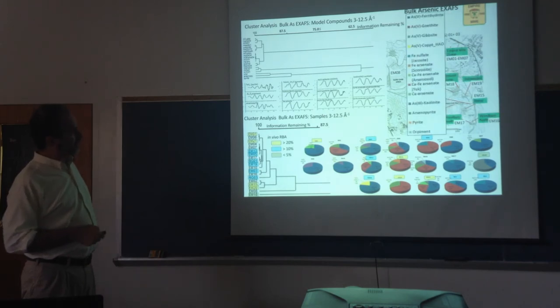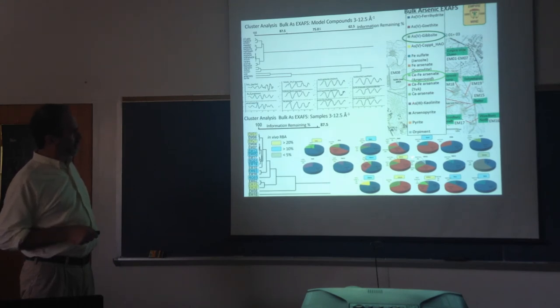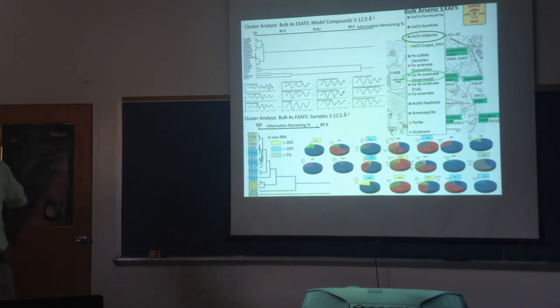Here's our color code, and some of the things they share are this calcium iron arsenate that we were looking for. There's not very much of it, this bright green, but two of those four samples have it, and they're the only ones that do. And then there's this phase we weren't really expecting at all, arsenic 5 or arsenate sorbed onto gibbsite, which is an aluminum hydroxide. Not that abundant a mineral, but it may be kind of a proxy for other aluminum-bearing minerals.